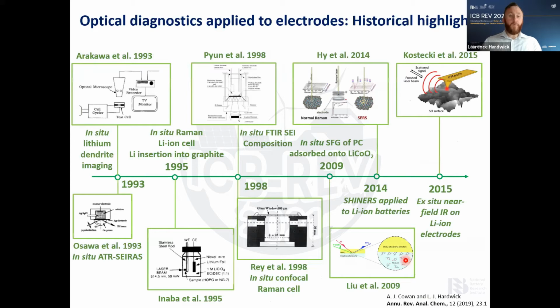Now to go to the more modern era, the new techniques start becoming much more advanced and more focused specifically on battery electrode investigations. So in 1993, we had the first demonstration of in situ lithium dendrite imaging with optical spectroscopy, and then Osawa first demonstrated surface enhanced infrared absorption spectroscopy, and we'll talk a little bit more about that. I'll show some of our data using this very nice technique. The first in situ Raman investigation of lithium insertion into graphite, the negative electrode in the lithium-ion battery, was in 1995, and the first study in 1998 used in situ infrared to look at the formation of this solid electrolyte interface.